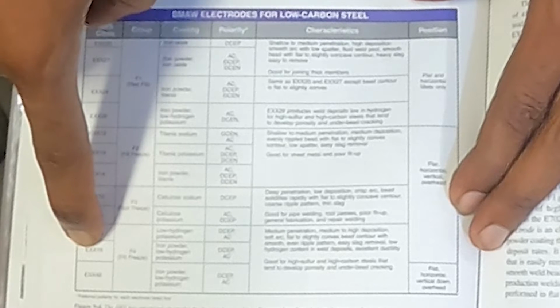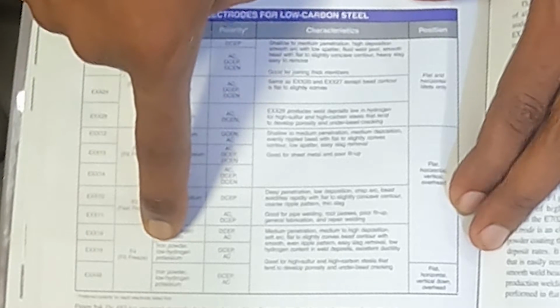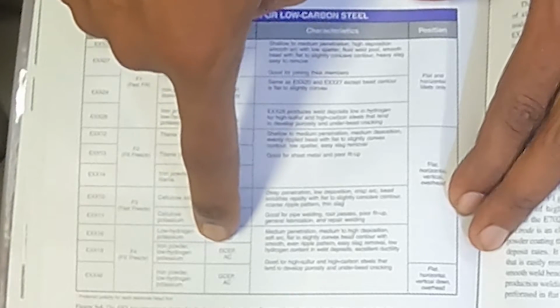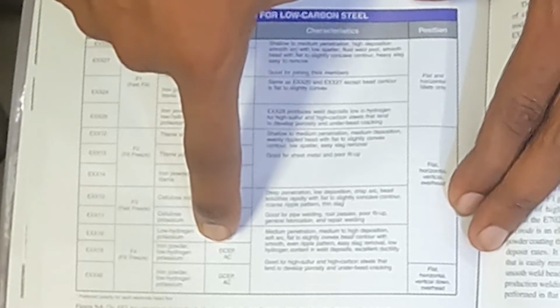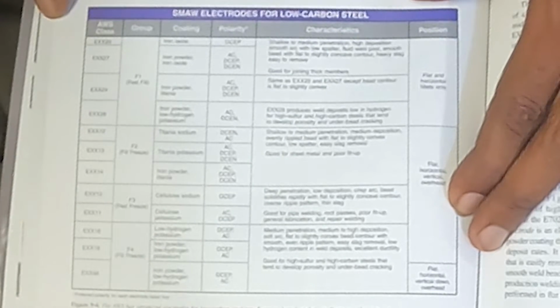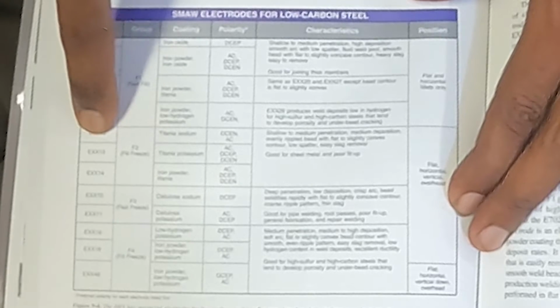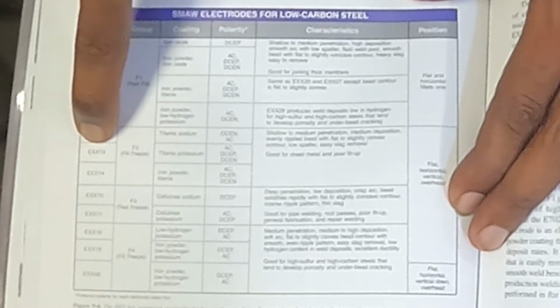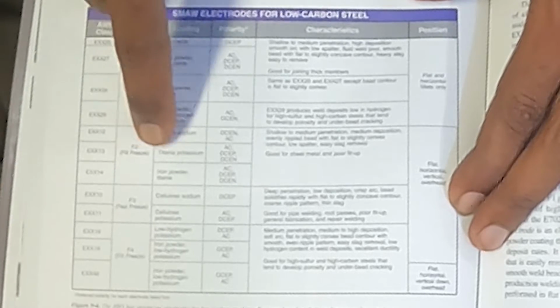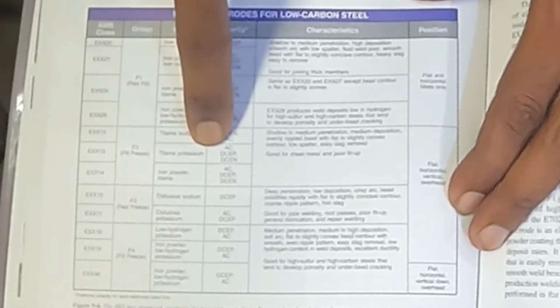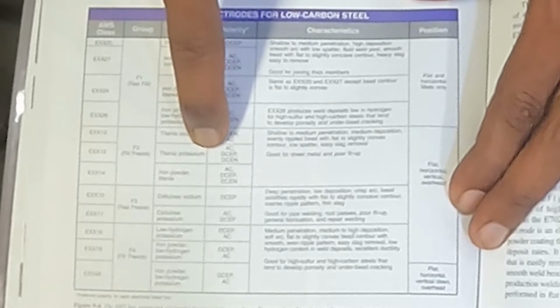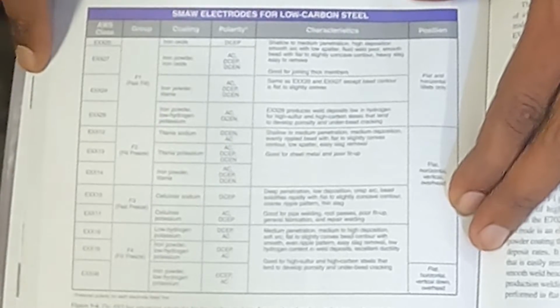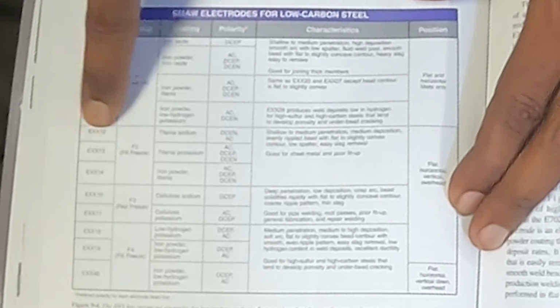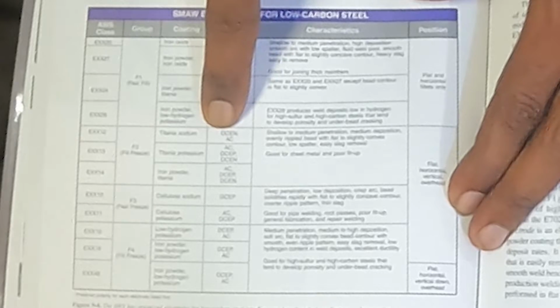It's a fill freeze rod, iron powder, low hydrogen, and it's DC electrode positive, or you can run it on AC, right? Okay, and then we were saying a negative rod is probably like a 60, I said 6013. So you see the 6013 is a fill freeze rod, titanium, potassium. It can run on all three polarities. So if you run it on negative, it's okay. If you run it on positive, it's okay. And if you run it on AC, it's okay. Okay? We have 6012. 6012s are electrode negative and AC only. So if you run it on electrode positive, you're not okay, right?